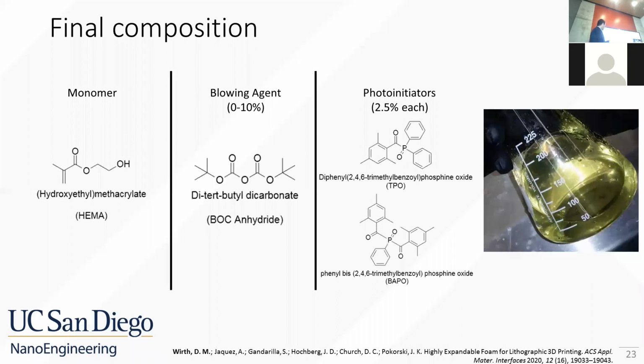The final resin we came up with was a base of 2-hydroxyethyl methacrylate, also known as HEMA. The blowing agent we chose was di-tert-butyl dicarbonate, also known as Boc anhydride. This is a non-traditional blowing agent; it's typically used for Boc protection of reactive amines.